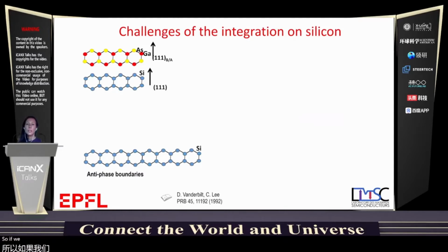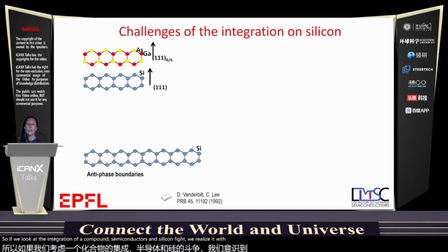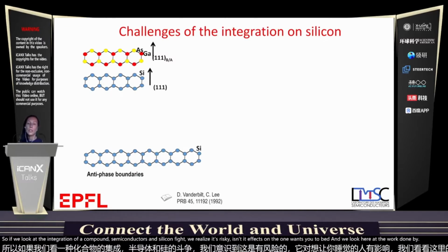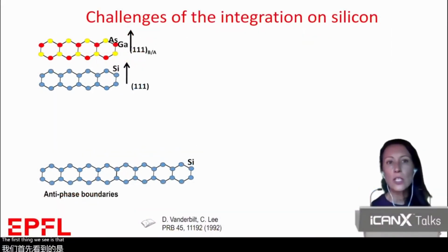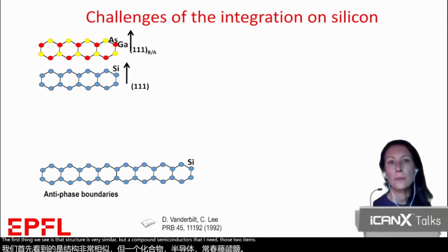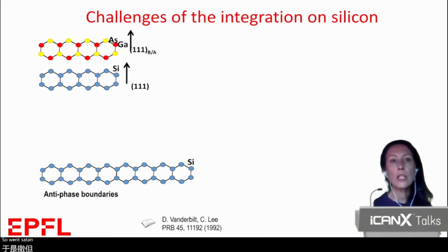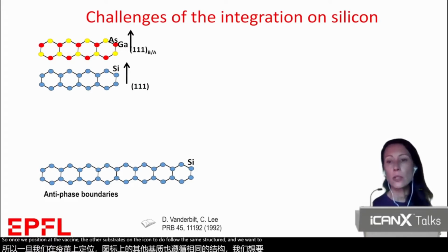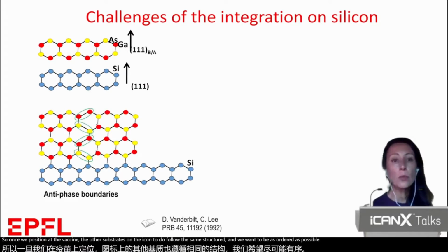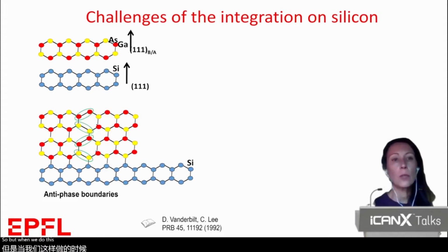If we look at the integration of compound semiconductors on silicon, here's a cut on the 110 plane, and we look here at the 111 direction. The first thing we see is that the structure is very similar, but compound semiconductors are made of two atoms. Once we position them epitaxially on the substrate, the atoms will follow the same structure, and we want it to be as ordered as possible. But if we don't do things well, it may happen, like you see here, that some atoms of the same type are bound.